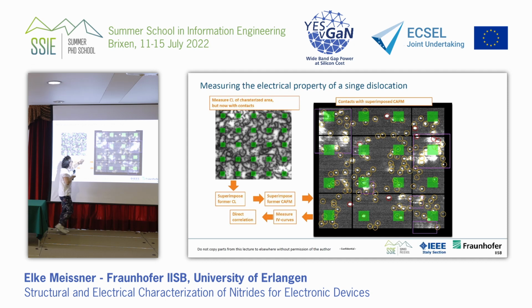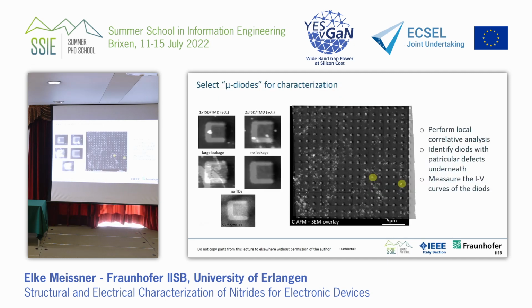And now we see, okay, at such green places, that will be later the device. And we have characterized the area before, and now we see, okay, what is going to be underneath this little device, and so we superimpose everything that we have measured, and we can make the direct correlation. And keep in mind that we always have to find this back on a microscopic scale, which is not so easy. And here you see now the CL image, and we see the little contacts here.